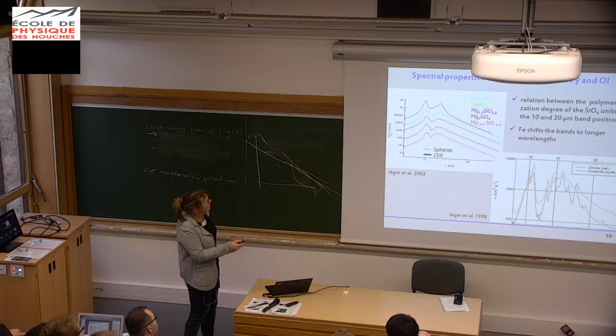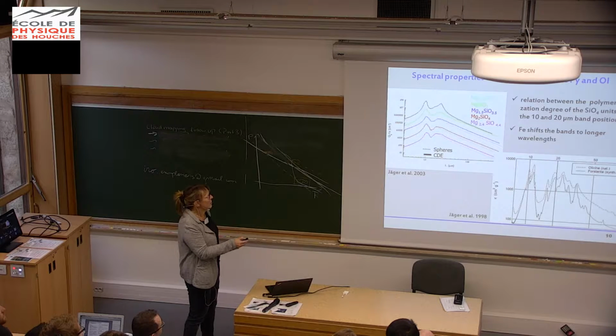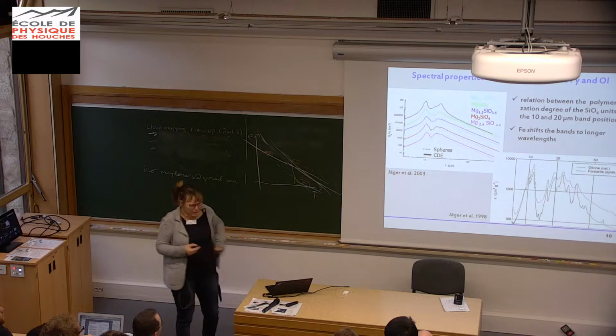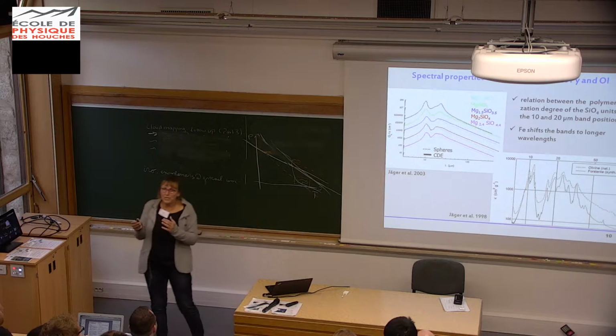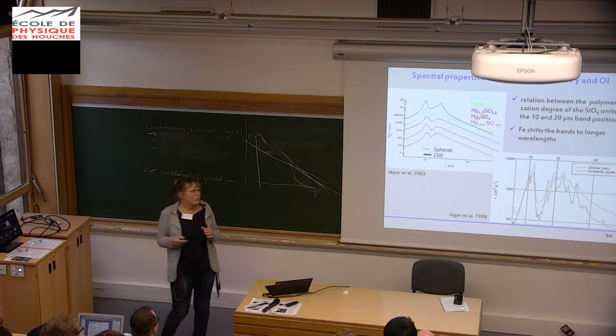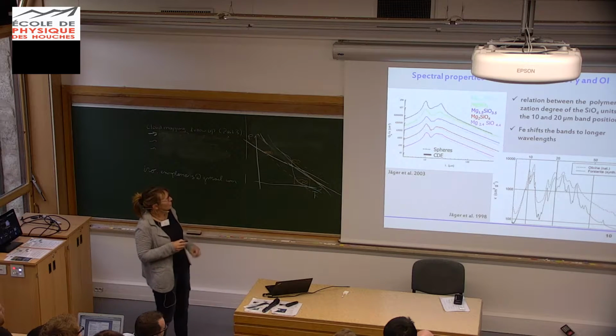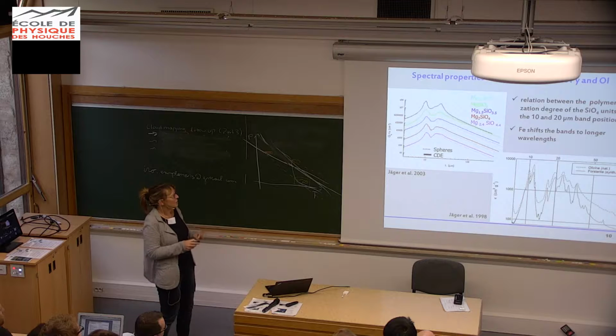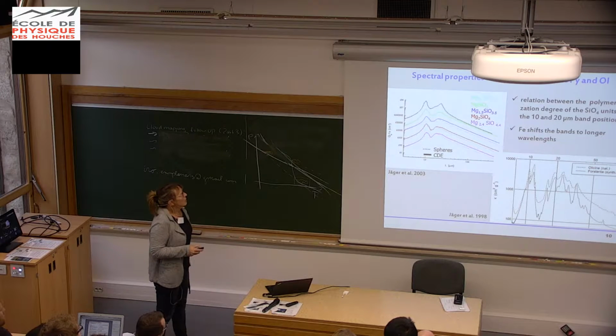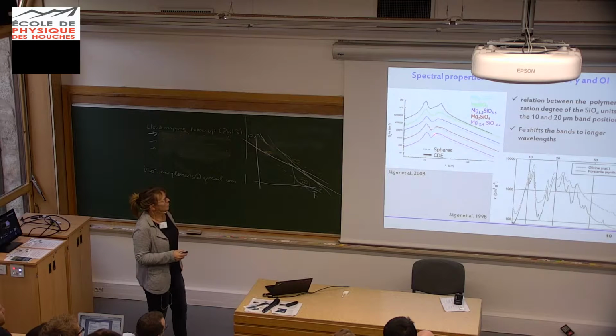And you go to olivine or a more non-stoichiometric olivine type material, you shift the 10 micrometer band to longer wavelength. This is expected because you change the polymerization degree of the SiO4 tetrahedra, and if you reduce the polymerization degree, you get this shift. The other band shifts to shorter wavelengths a little bit.